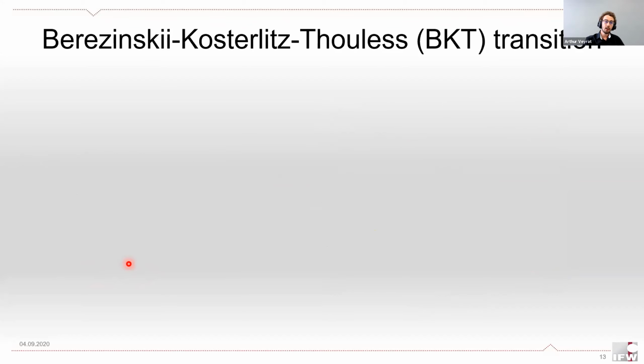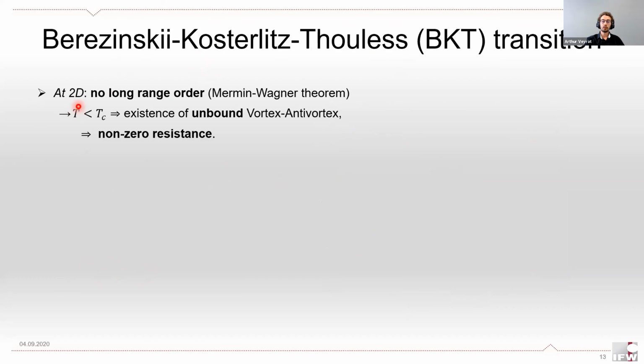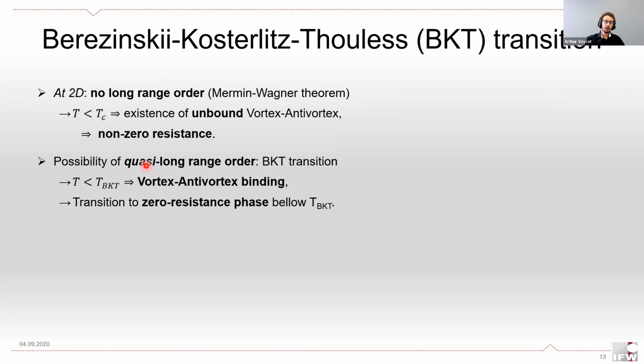One interesting effect that we can expect to see in two-dimensional superconductors is the so-called Berezinskii-Kosterlitz-Thouless transition. As you may know, in 2 dimensions, there is no long-range order possible, according to the Mermin-Wagner theorem. So that means that for a superconductor, even below the BCS critical temperature, there will exist some vortices and anti-vortices that will be unbound and will drift away when a current is applied. They will drift in opposite directions. This will cause phase fluctuation, which will result in a non-zero resistance, even below the critical temperature. But there is the possibility of a quasi-long-range order, and that is the essence of a BKT transition.